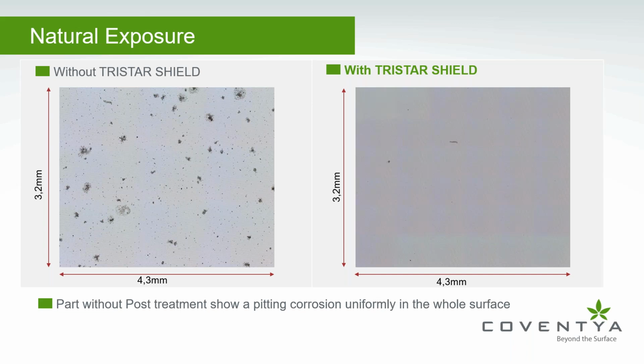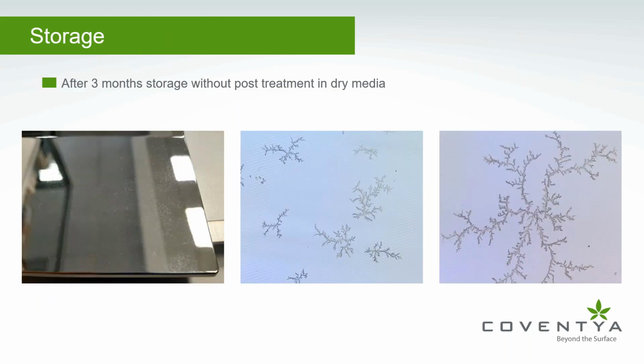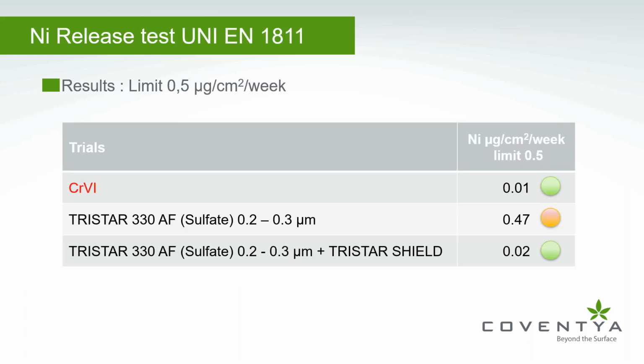As shown in this photo, all trivalent chromium plating shows some salification or corrosion beginning. It happens because the surface layer has not been treated with a protective post-treatment. After Tristar 330AF, using Tristar Shield allowed solving both natural exposure and storage issues, fully preventing surface corrosion from starting. Well, as you can see from this table related to the nickel release test, the result of Chrome 6 is comparable to the combination of Tristar 330AF and Tristar Shield, which passed the test in an excellent way. Even Tristar 330AF passes the test.